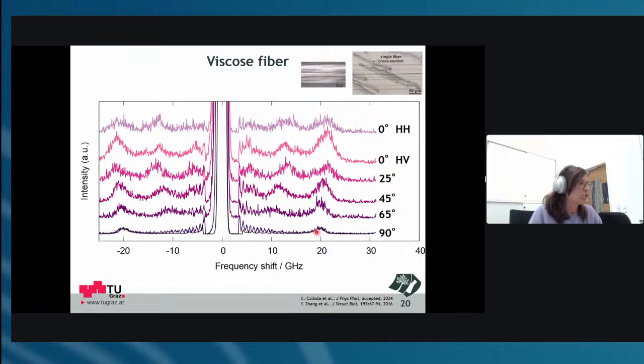And then we also compared this peak to the backscattering, so this 180 scattering geometry. As you can see down here at 90 degrees, I only did the measurement there, that's why it's here. These two are overlapping. So the 90° measurement and the 180° measurement are overlapping, which means that what we measure here in the back is, if you wish, an artifact, or it is just the backscattering signal also in this geometry. So you measure two geometries with one. This has been reported in literature for glass fibers already, and it is an indication that the material has very good optical waveguiding properties. But for me, it was very painful, because any evaluation we would do for the stiffness tensor would just not make sense, because it makes no sense that this stays like that.